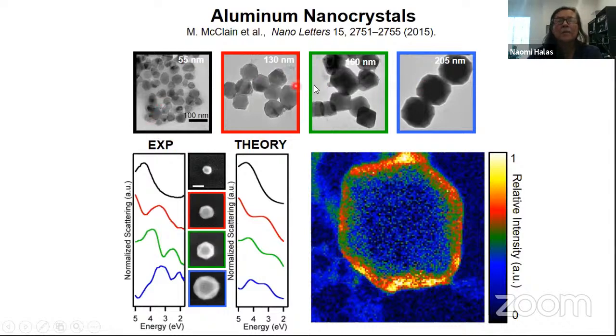And as you vary the size, you can vary the wavelength of light that's resonant with the nanoparticles. You can vary the resonant energy of the plasmon in the nanoparticle. As you make it larger and larger, you can lower the resonant energy. And so this is a TEM image of the nanoparticle. Aluminum is a very reactive metal, as many of you know, and it is always terminated by a very thin oxide layer. And so this is actually what you're seeing in this TEM image, the oxide layer surrounding the otherwise crystalline nanoparticle.